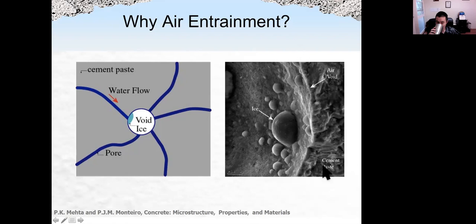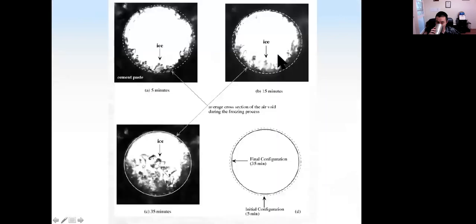And this is cement paste. We can also see from here, this is air inside cement paste after ice formation. After 5, 15, and 35 minutes, we can see clearly ice grows inside this air, so stress will be released.